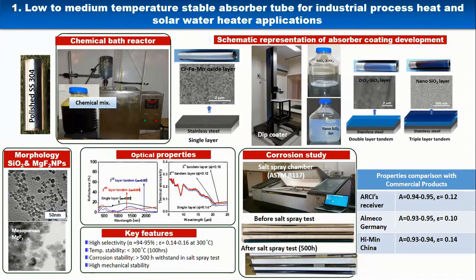So what we are doing is using a special chemical mixture at process temperature. We oxidize the metal, forming a very tiny oxide layer on the stainless steel, which gives it an optical absorptance of around 90%. And the second layer we developed from a sol-gel process, a zirconia silica composite, and then we put it over that as the base absorber layer using a dip coater.